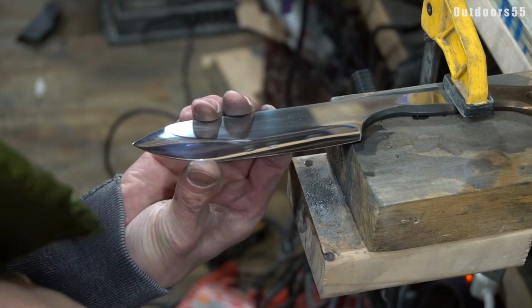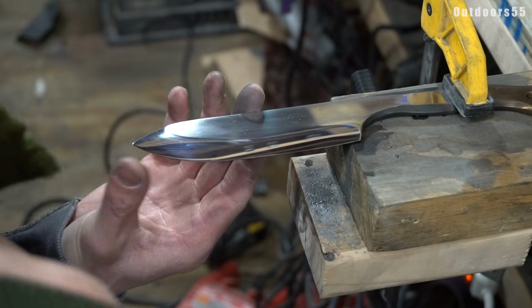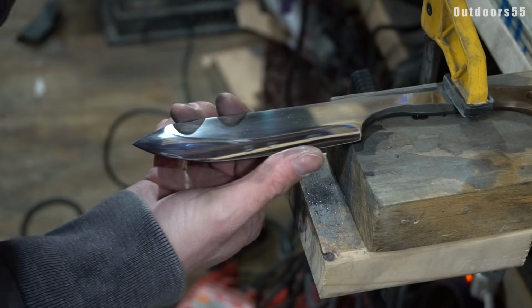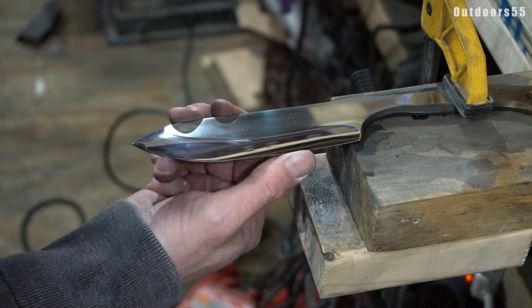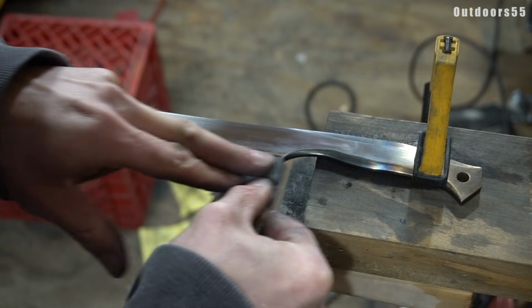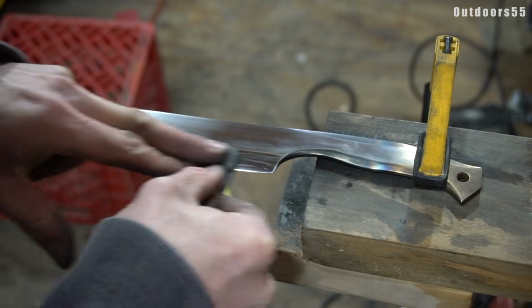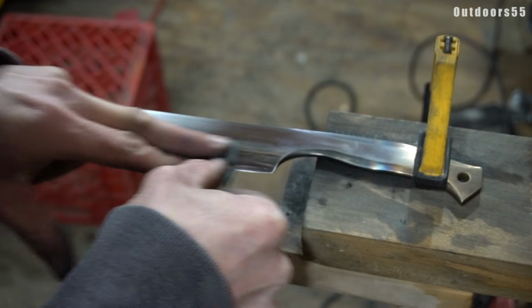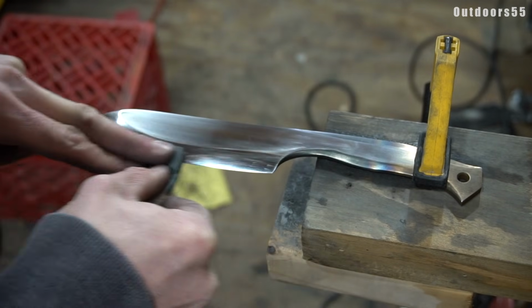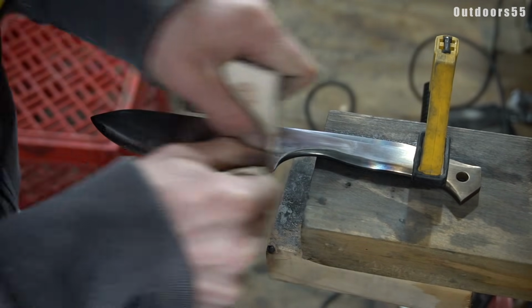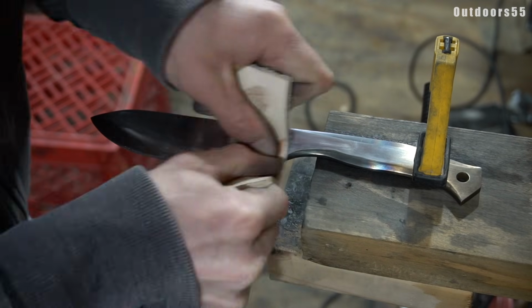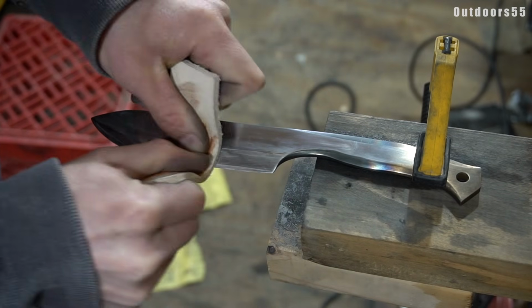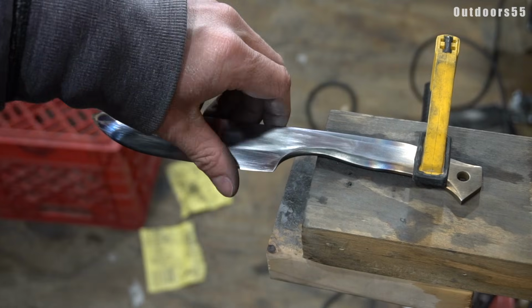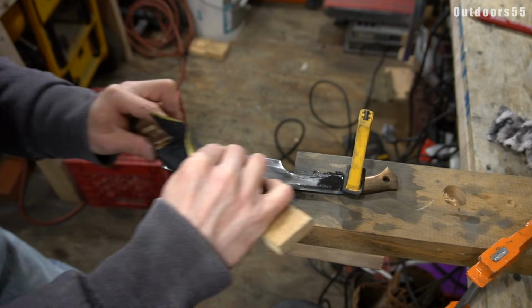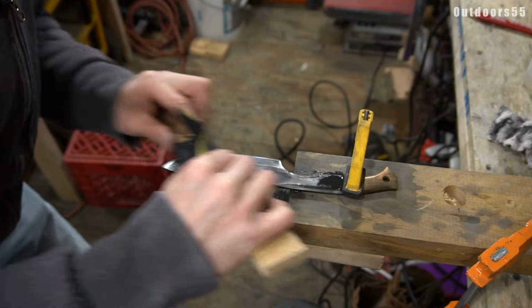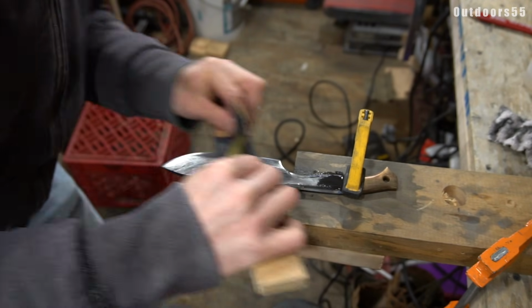Now because I used a grinder with a flap disc for the bevels, this knife has what's called a convex grind, and just through the hand sanding and finishing part will end up being sharpened. Basically the bevel ends up being curved all the way down to the apex, meaning there's no secondary bevel on this blade. Now I could go into a whole video on sharpening a convex blade, but for the sake of time I'm just going to have to leave it at that. You're basically just working the edge with sandpaper until you form an apex. I'd advise against going back to the grinder for sharpening, as the grinder may introduce too much heat into the steel and ruin your temper, in which case you'll have to start all over again with a heat treatment.